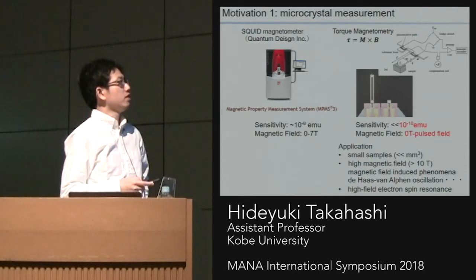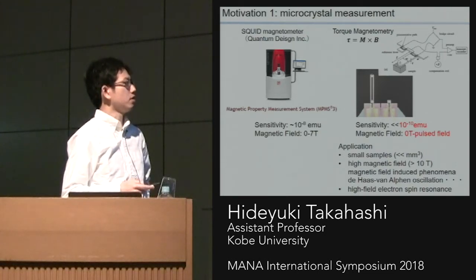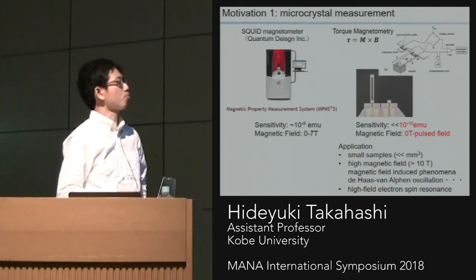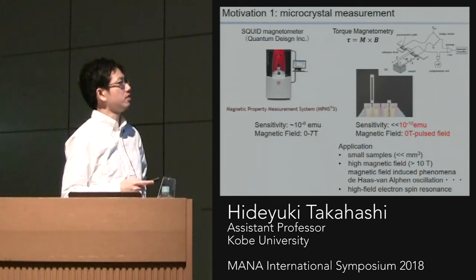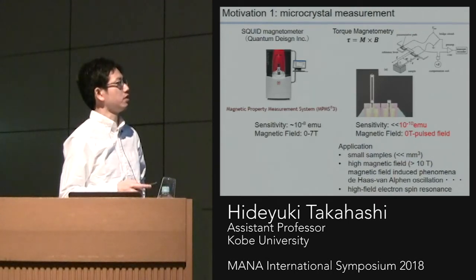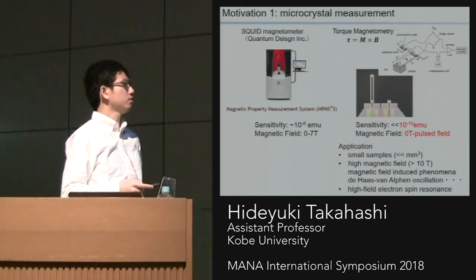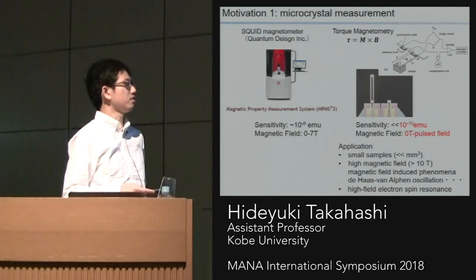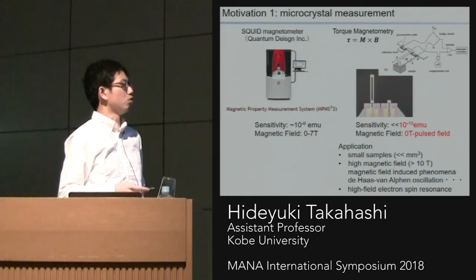In such a case, we use torque magnetometry with a MEMS device. In this example, it is a piezoresistive cantilever. This method is very suitable for a simple measurement setup, and we can achieve much higher sensitivity. In this method, we measure the magnetization by measuring cantilever deflection caused by the magnetic torque. In addition to its very high sensitivity, another advantage is that this method can be used at very high magnetic field and at low temperature.